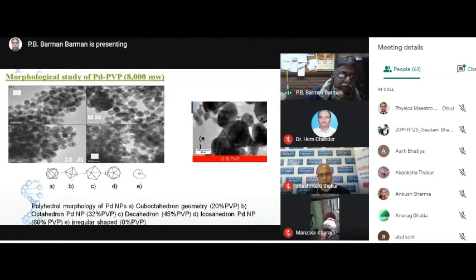So these are the 4 shapes we got when we changed the PVP from 20, 32, 45, and 60%. This is a very, very important result, and we have published this result too - that this shape actually plays a role in the sensing mechanism in my hydrogen sensors. This is a very, very important finding.